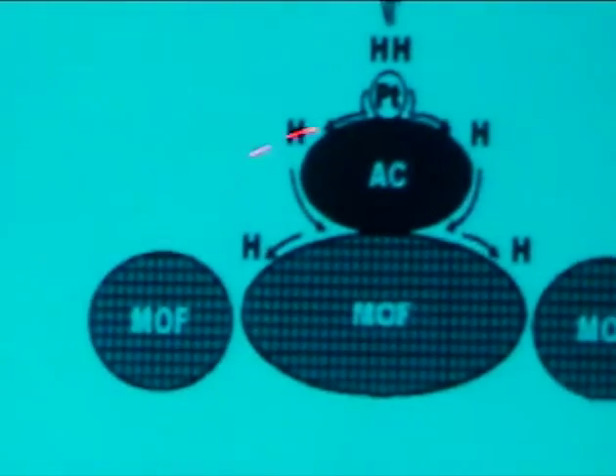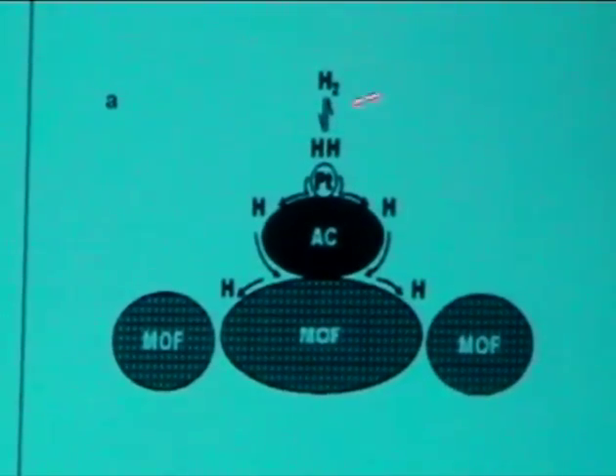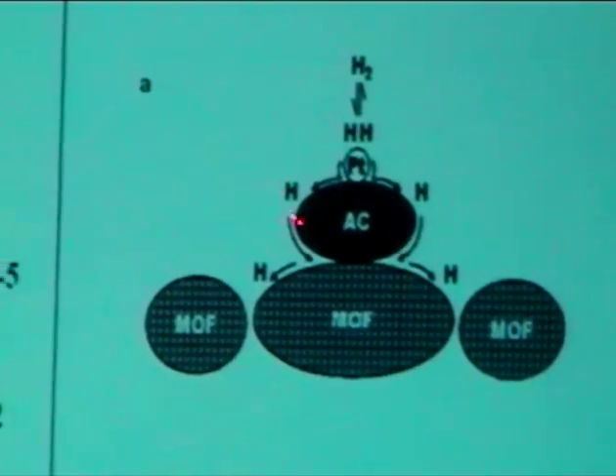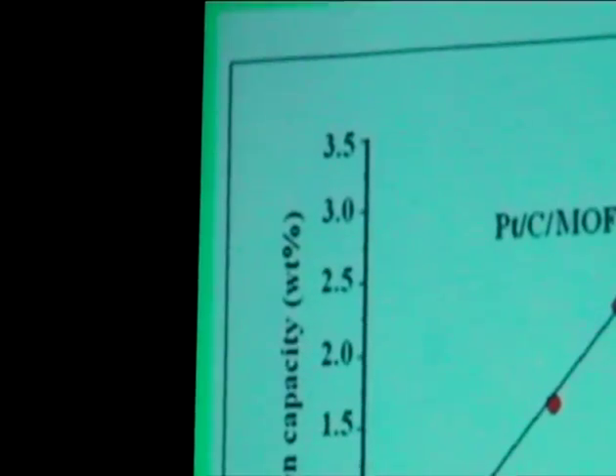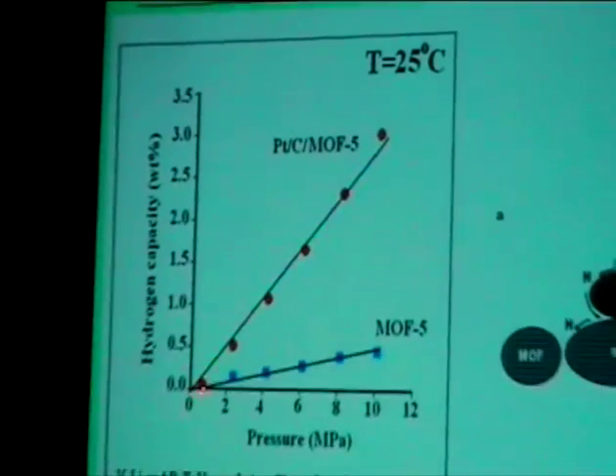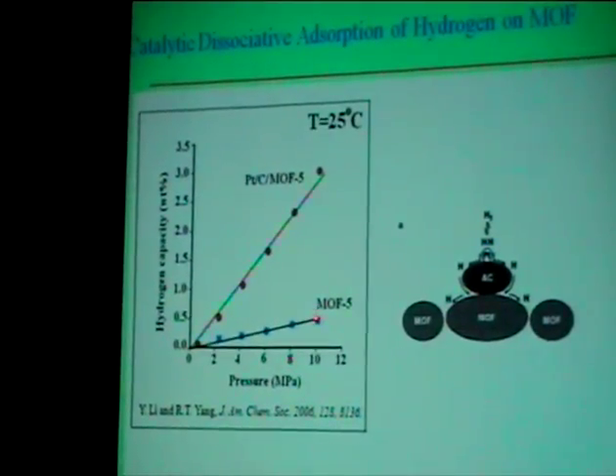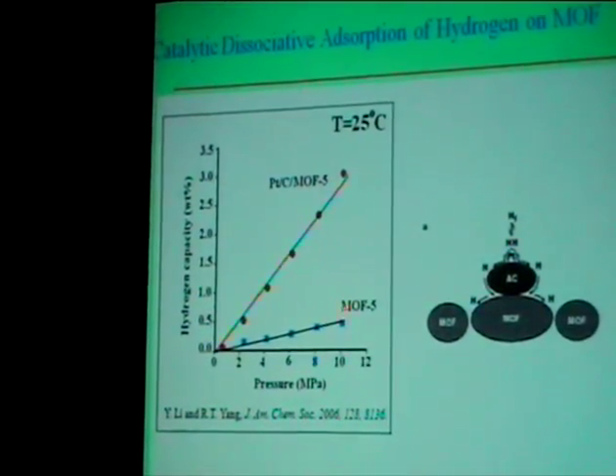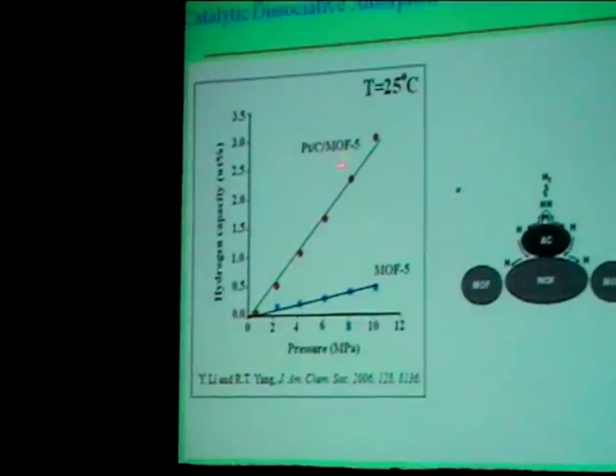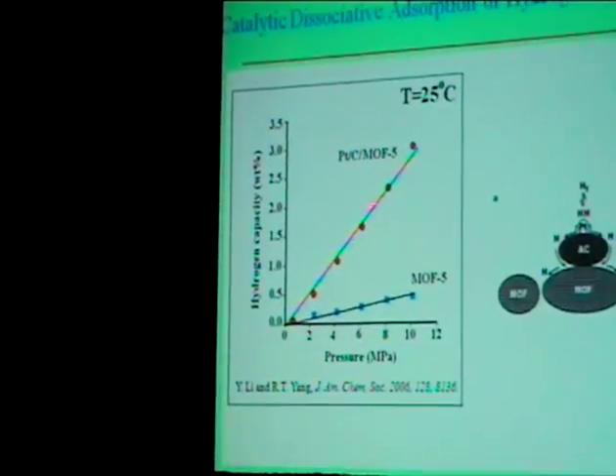They simply doped platinum on activated carbon, and mixed it with the MOF. They would like the hydrogen to dissociate to hydrogen atoms, and the hydrogen atoms diffuse from the platinum to the activated carbon, and then diffuse to the MOF. And these hydrogen atoms should have a strong interaction with your MOF. So they did the experiment. You can see one is the MOF5 without the catalyst. The capacity is lower, even at 10 megapascals hydrogen pressure. And if you combine the platinum carbon with the MOF5, you can see the hydrogen capacity jumps to 3%. So that's the basic result.